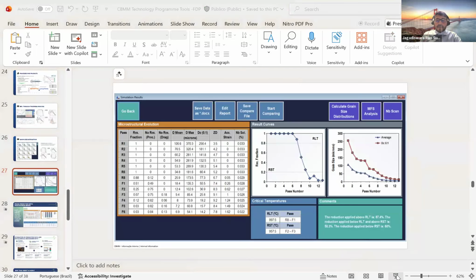The recrystallization fraction: for example, if you see roughing mill 1 to roughing mill 6, it is showing 100% recrystallization going on. The graph here also shows complete recrystallization. When the temperature comes down, it shows how much recrystallization is going on, the percentage of the non-recrystallized area, and the percentage of the solute drag effect. Along with that, the strain accumulation in the material is also shown.